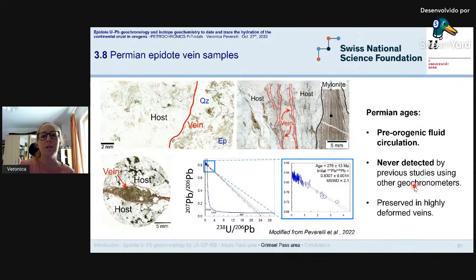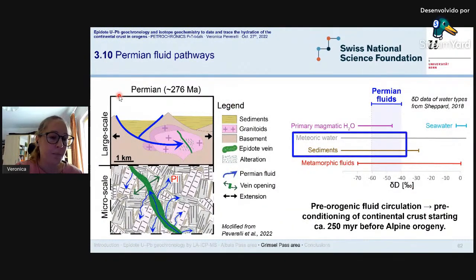This is actually really important because it's the first ever evidence, or the first hard data that we have, for pre-orogenic fluid circulation in the study area. And these ages had never been detected by using other geochronometers. So you see that epidote is doing something new. And we know that in the Permian, the area was affected by transtension. And so our hypothesis is that the epidote-forming fluids originated at the surface as meteoric water, and that they exploited thin rift faults to infiltrate the continental crust, interacting with thin rift sediments. And this is actually consistent with hydrogen isotope data of the Permian epidote-forming fluid.